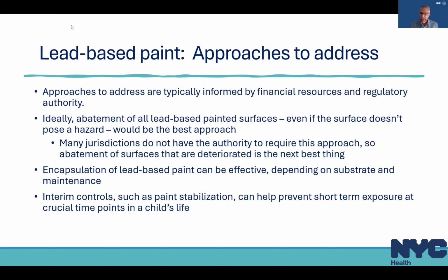Encapsulation, which is the application of a thick paint that binds to lower layers of paint, can be effective, but it really depends on the condition of the substrate it's being applied to and whether or not ongoing maintenance of the encapsulated area is occurring. And finally, interim controls, which is basically bringing the paint to an intact condition, can help prevent short-term exposure at crucial points in a child's life. So there are windows where risk is greatest for childhood exposures, and if resources are limited, sometimes interim controls can prevent exposure on a short-term basis.